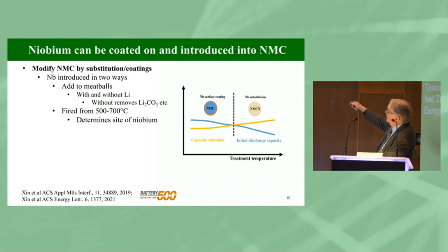We added niobium in two ways, either with no lithium in it or with some lithium in the solution. If we don't have lithium in the solution, then with these very high nickel contents, 80%, we always have lithium carbonate or lithium hydroxide on the surface. But the niobium in there, it removes that lithium, forming our lithium niobium oxide films.